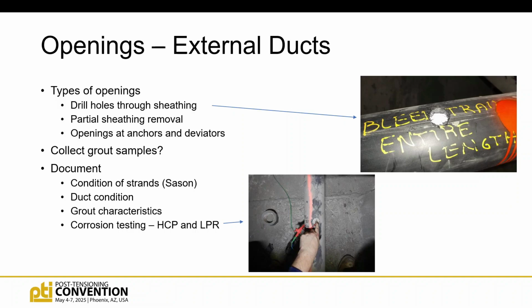So we don't typically take grout voids out of the holes. We will take grout voids out of the larger openings on the externals. Again, we're going to look at strand corrosion. We're going to look at whether the duct is cracked or damaged in some way. And then we're going to qualitatively say whether the grout is white and powdery and flaky. Is it dark, hard? Is it wet? Those kinds of things. We may do some half-cell potential measurements and linear polarization tests as well.